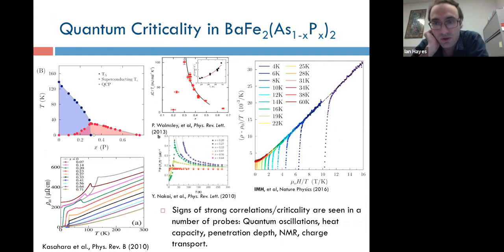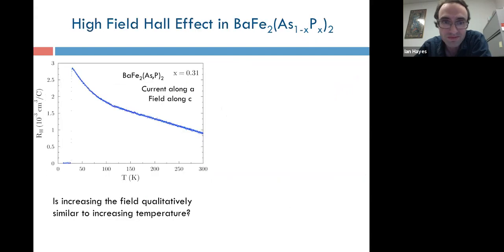Now, I probably don't have to introduce phosphorus-doped barium-122 here, since we just heard a lot about it. But what I want to highlight here is that the observations we made previously about parallels between the field dependence and temperature dependence in the resistivity motivated us to look at the field dependence of the Hall coefficient and to ask whether there was some way in which the field dependence there gives us another way of characterizing the strange metal behavior, what it's correlated with and where it might be coming from. That's really the motivation for the data that I'm gonna show you now.